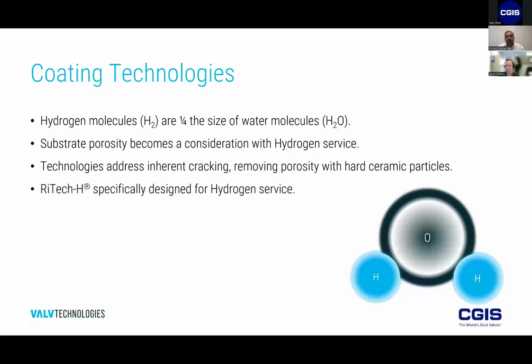It was technology that was derived from the aerospace industry in the 60s and now has filtered its way down to valve design. But when it comes to coatings, which are really there as a hard-facing technique to prevent against wear and resist wear over time as valves cycle, porosity becomes a design consideration. Whereas before, if a coating was perhaps 0.5% porous, which is one of the best on the market, I mean, typically most coatings have about 6% porosity, even 0.5% is not good enough because hydrogen can still escape through that.